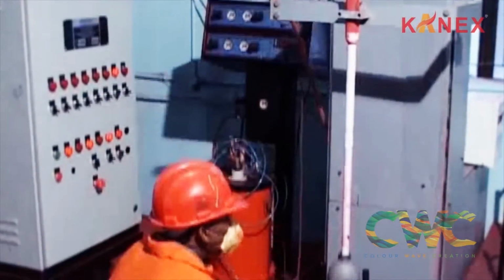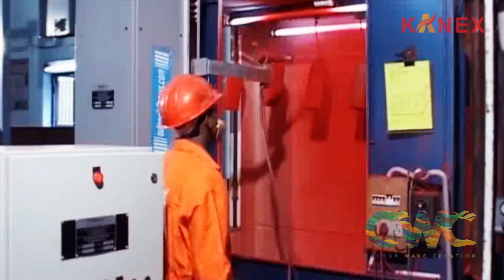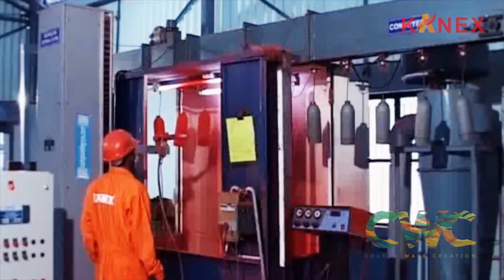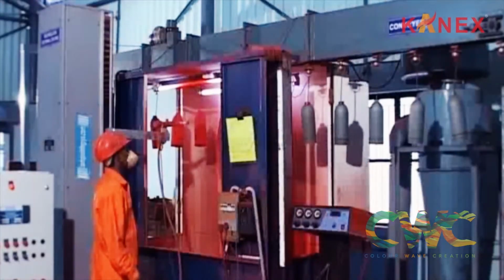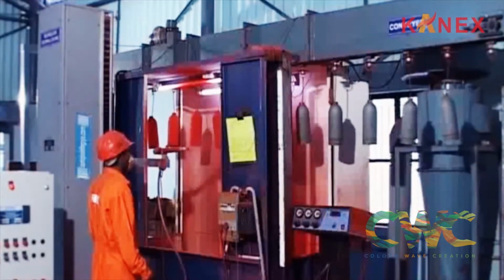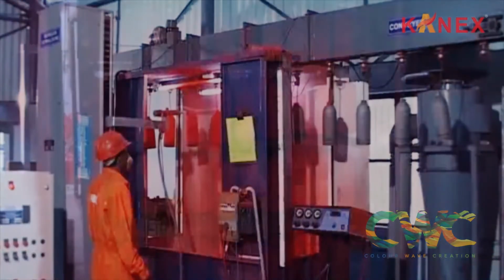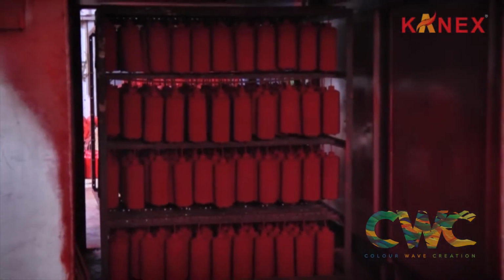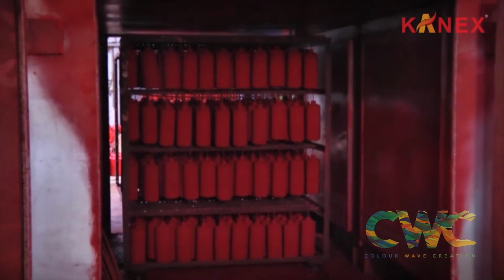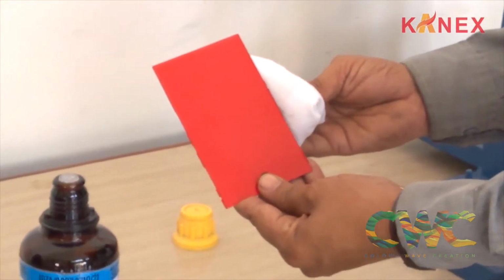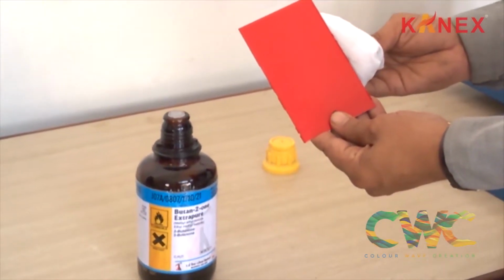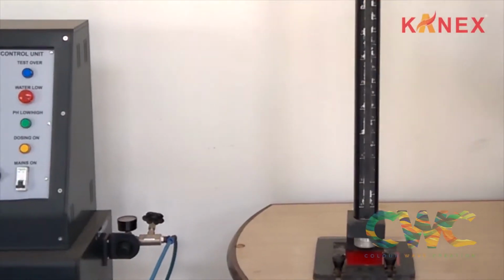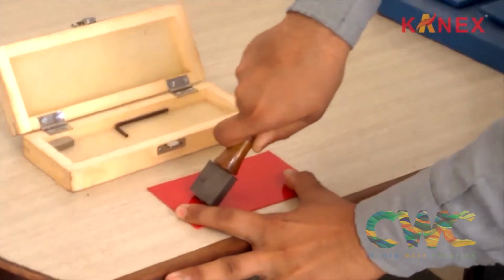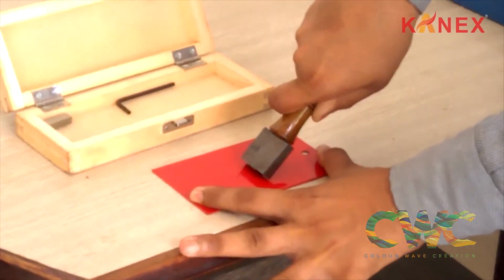The powder coating is hard and scratch resistant. It is also resistant to acid, alkali, and other chemicals. The technique involves adhesion of powder by an electrostatic charge and curing in an oven at 200 degrees centigrade for 10 minutes. Each lot passes through various tests like methyl-ethyl ketone, impact, conical mandrel, crosshatch, and DFT measure for checking